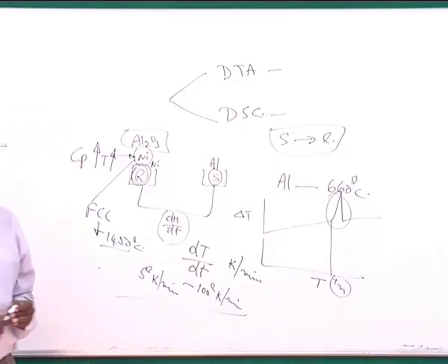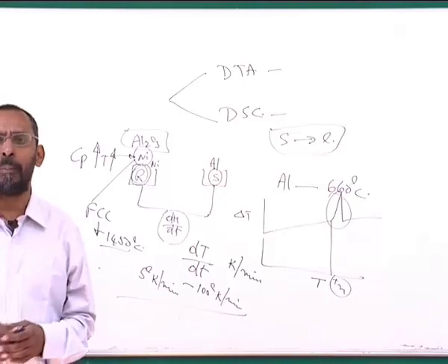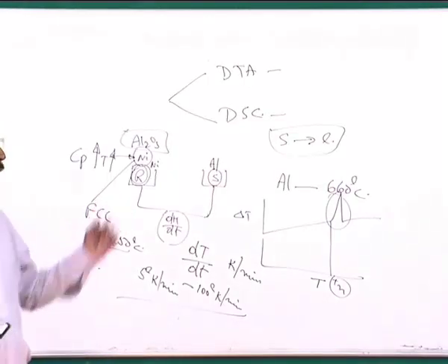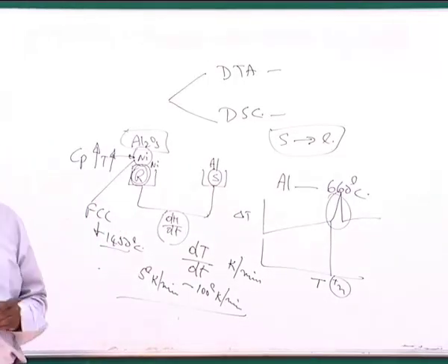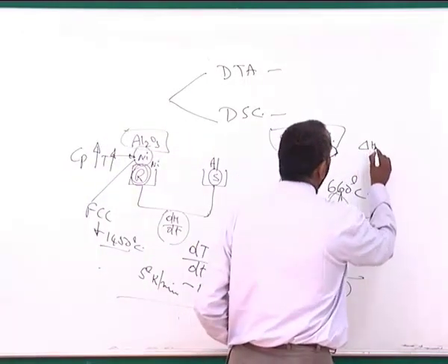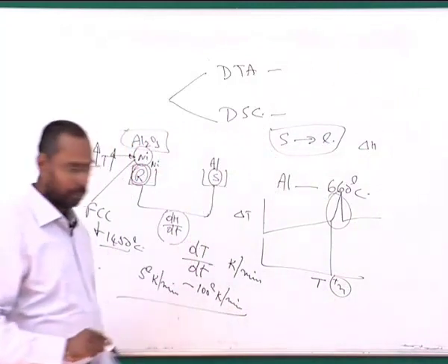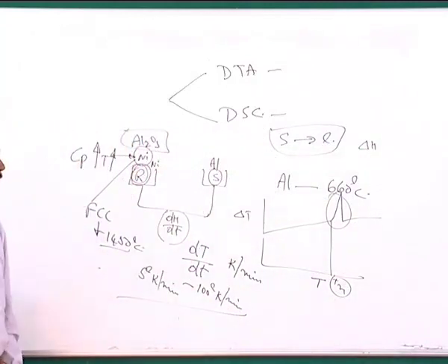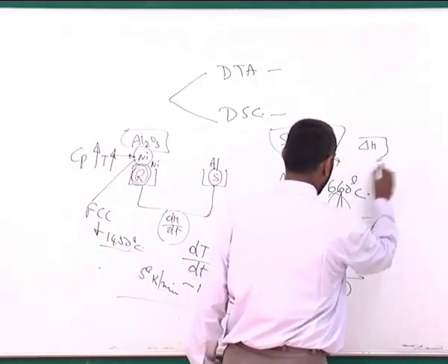So we were talking about thermal analysis. We said there are limitations in the normal thermal analysis, which is what we call the cooling curve methods, because wherever the delta H is small for a particular transformation, that cooling curve method does not work out. As a result, particularly solid state transformations have a very small delta H.